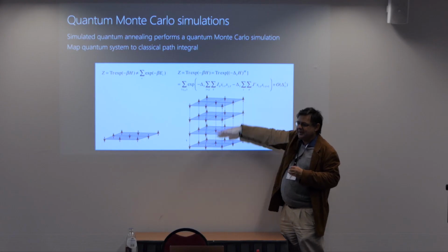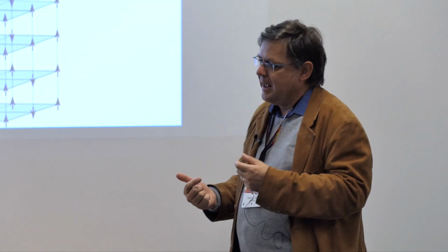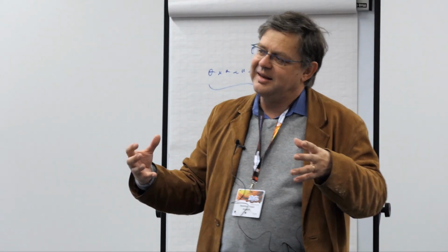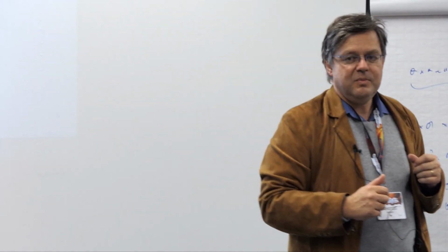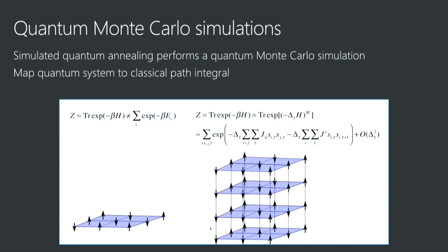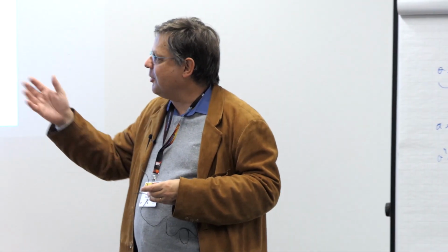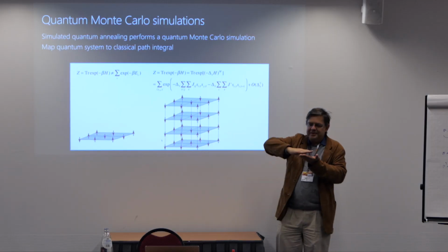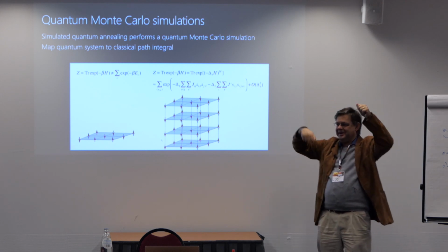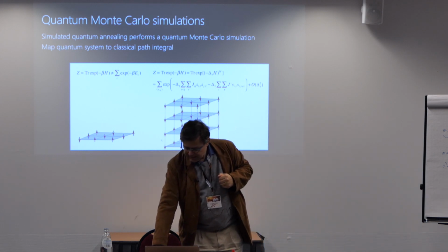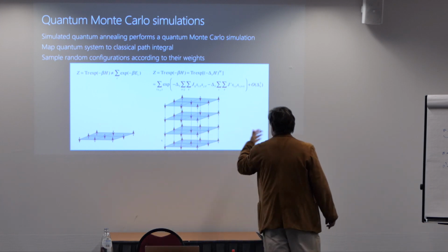So I do lots of small time steps, and I map the 2D quantum system, in this case, to a path integral where I propagate that state in imaginary time. Then I sample over all possible intermediate states. So this is the standard path integral with which I can map it. And if I take such a quantum spin model, in this case in a transverse field, then I map it to a classical spin model in a higher dimension. So I can simulate any quantum system by simulating the path integral in one higher dimension. I can do that also for this quantum annealer. So I have my quantum spin glass here in a transverse field, and I simulate it by simulating the path integral with lots of time slices, and now I just flip my spins randomly in a Monte Carlo simulation. This is what I do to simulate the quantum system here.